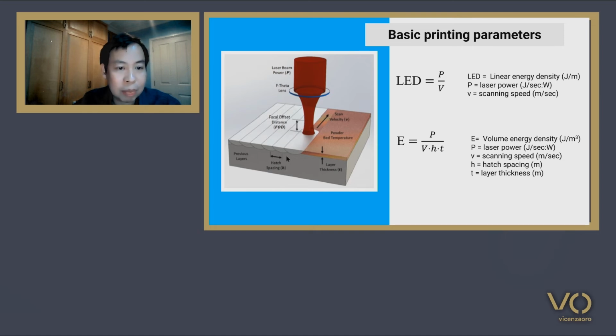Here we also have hatch spacing. That's the distance between each of the scans. And then there's a layer thickness. This is the thickness of the powder that has been poured over, and this is the movement of the stage that lowers down. Usually we do this in maybe 25, 40, 50 microns.